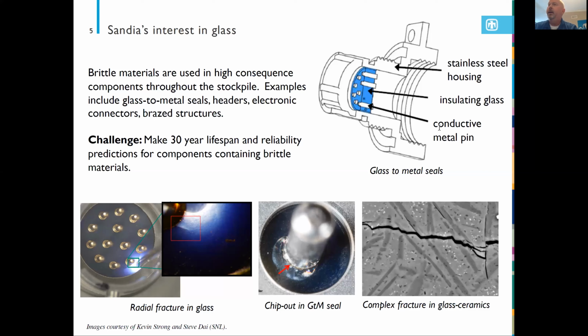And not surprisingly, these seals fail. I wanted to share a few of the ways that they do fail. These are the lower figures. On the lower left-hand side, we're looking at one of the connectors head-on into the pins. The bronze colors are the pins that are sticking through the glass, which is the blue material in between each one of the pins. The quantity of pins is not important. You could have a single pin or a multi-pin connector, but the inset really shows exactly what's taking place here. The glass undergoes some very unique stress states. And as a consequence, often what happens is you might have a radial crack originating from one of these pins, or you might have a delamination between the housing and the glass itself.